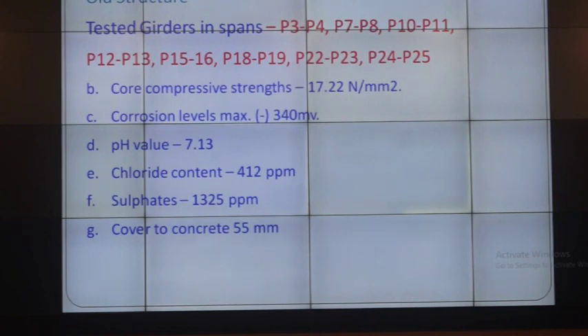Please note down, when you make it, don't say carbonation has happened. Carbonation can happen from 11 to 7, anything can happen. But if you say 7.13, then people will understand, yes, this has got a problem with that. Then chloride content is about 412, so margin, sulfates okay, cover is by and large okay.